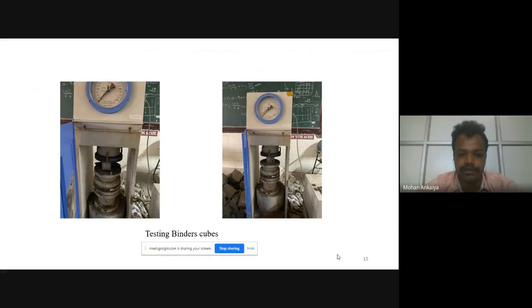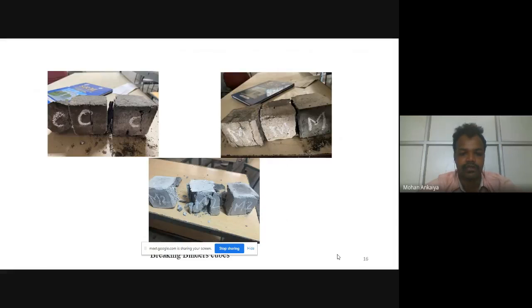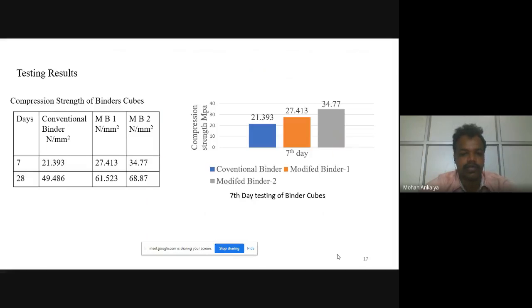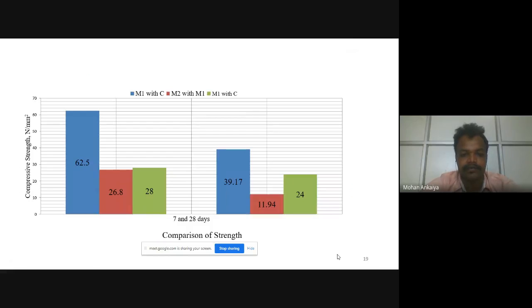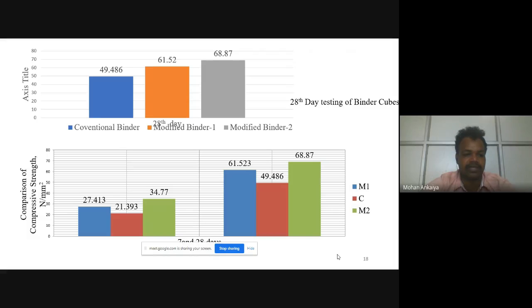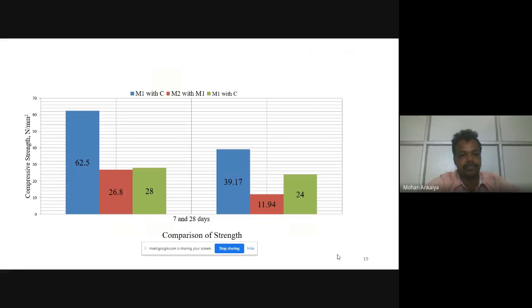As of now, we are just displaying the cube results. These are the breaking patterns of the cubes. We can see that all the cubes failed by crushing. Compared with the conventional binder, modified 1 and modified 2 showed far greater strength. These are the comparisons of the strength for M1 with the conventional binder and M2 with M1.